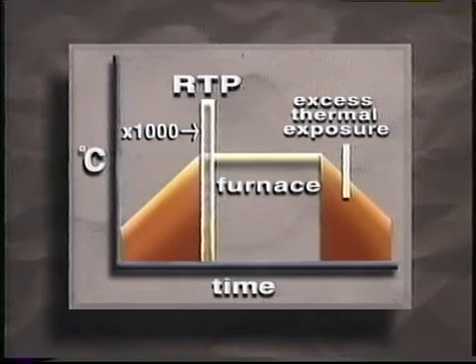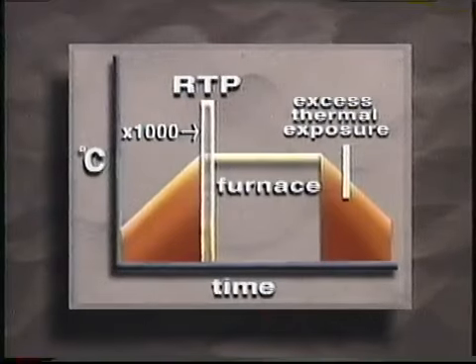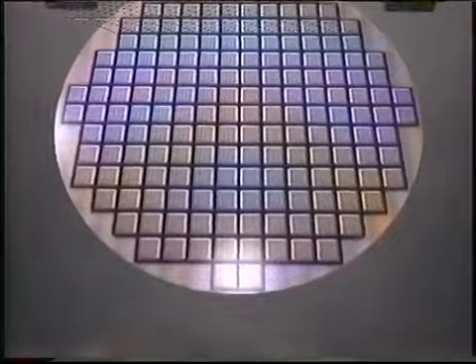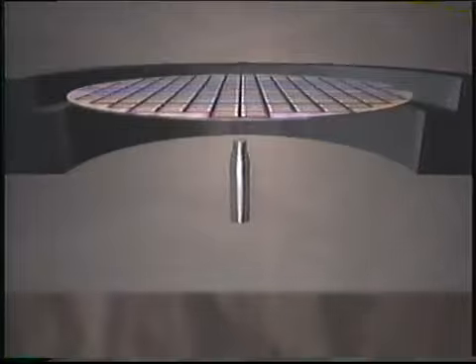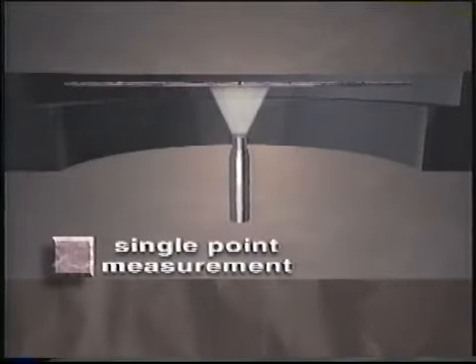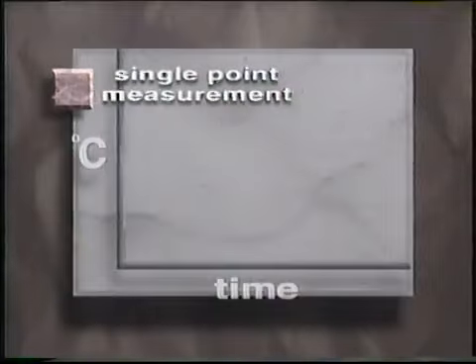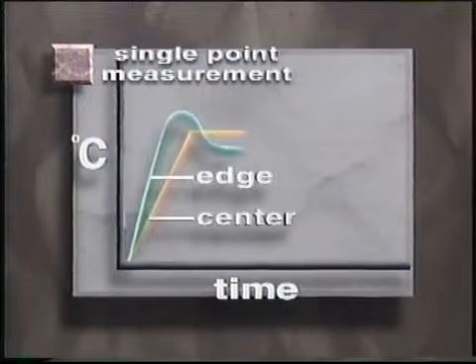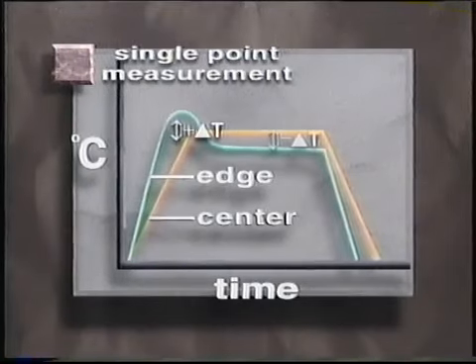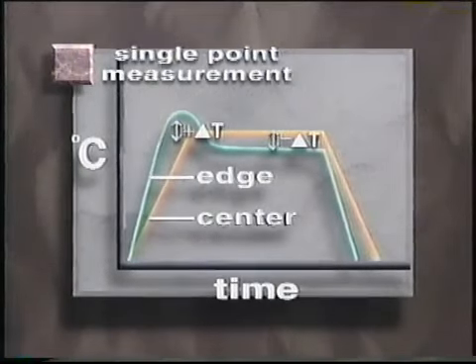The challenge for RTP is how to ramp quickly while maintaining temperature uniformity. Present-day RTP systems use a single non-contact optical pyrometer to measure a wafer's temperature at the center. This single-point measurement, however, can't sense center-to-edge temperature differences. The result is non-uniform heating, which causes slip defects and undesirable process variations.